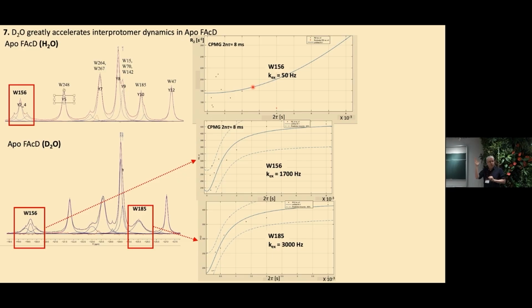with light. We can create an excited state, but then we can measure its lifetime as a function of refocusing pulses in an NMR sequence. So we can measure a lifetime with one refocusing pulse, 2, 4, 8, 100 refocusing pulses, get a different number, and measure a curve. So instead of one number, a lifetime, we can actually get a rate as a function of the spacing between the refocusing pulses. And so if we have an experimental curve like this, it becomes much more reliable to then fit that curve to a specific dynamic model.